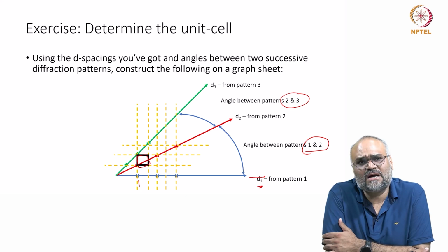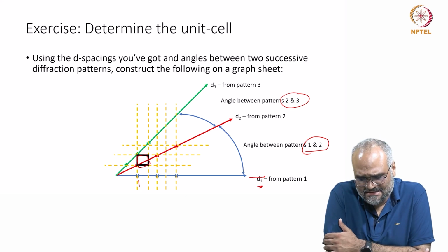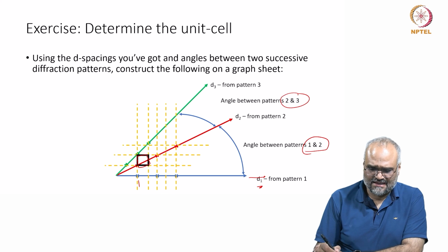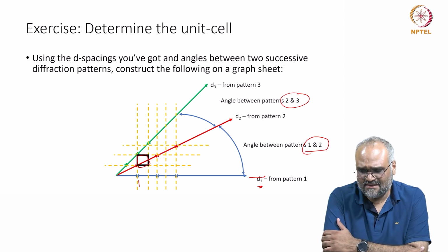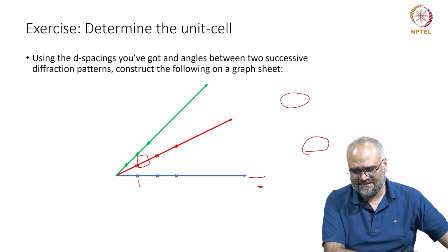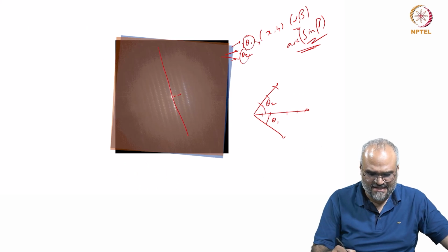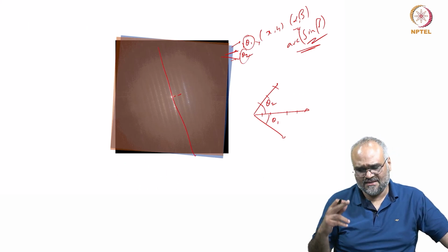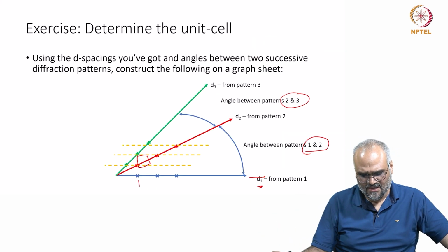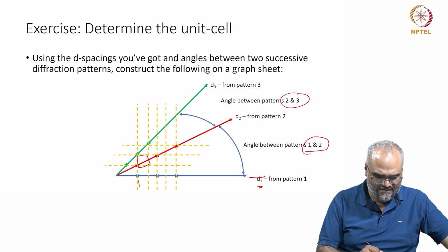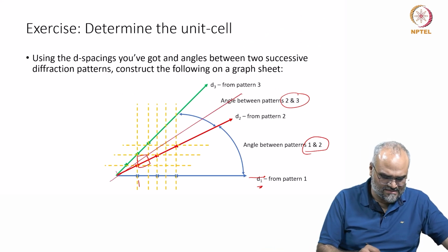So, to correct for that, my advice is to maintain this common direction, which was the closest placed set of reflections along this line, and try to get one more diffraction pattern which would potentially be somewhere here or somewhere here.